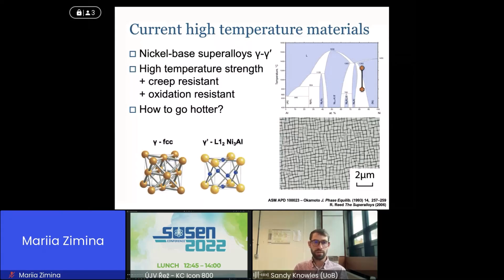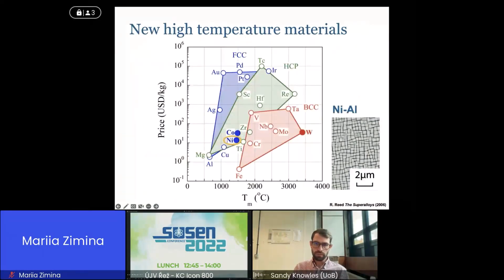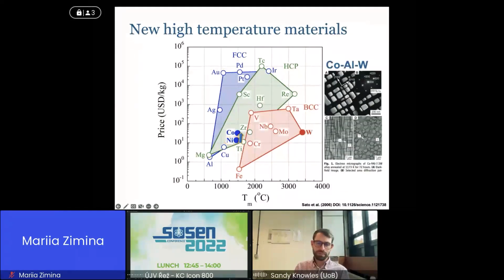Nickel superalloys are an exceptionally good material, but getting improvements has become ever harder. If we really want to go to higher temperatures, and if we also want to go into nuclear environments where we have concerns about helium generation from nickel, or radiation damage within the FCC matrix, we might consider some other options. In the aerospace community, there's been a shift trying to increase melting temperature. That's the first proxy for high temperature performance: what is your melting point. That gives you an absolute upper limit. There's been quite a lot of work with many research groups looking at changing from a nickel base to a cobalt base. That gives you nearly 150 degrees C potentially improved melting point, which could give you an extra 150 degrees C operation performance.